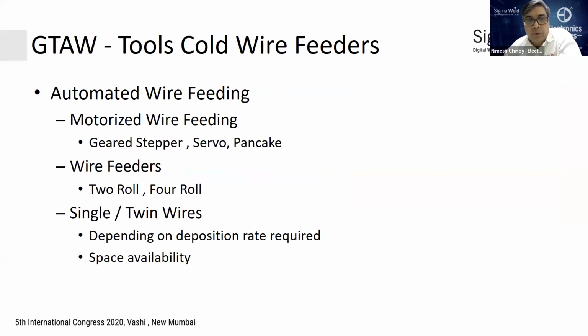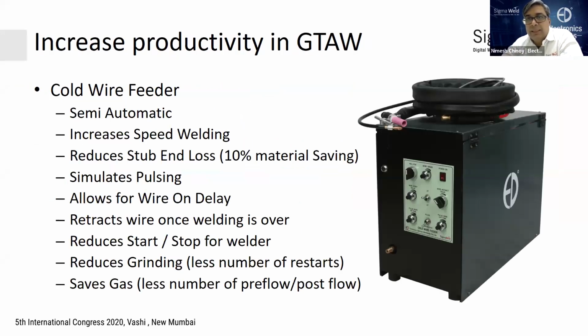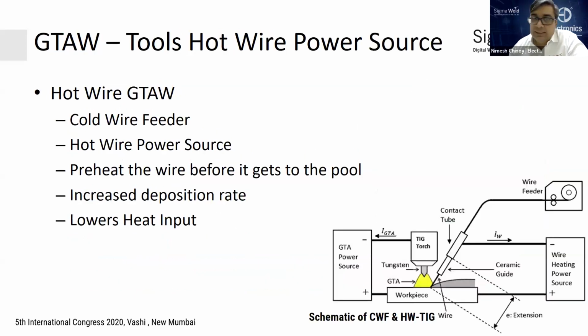You can go in for cold wire feeders, which are single wire, twin wire. They look something like this. They use a full spool. So you have 10% saving on material costs because you have that much less stub losses. You can increase your weld speed by up to 30 to 40%. And it allows a lot of, because there are less number of start stops, the number of grinding reduces, the amount of gas consumption reduces, and the operator convenience is much higher. The same operator can produce close to about 30 to 40% more speed.